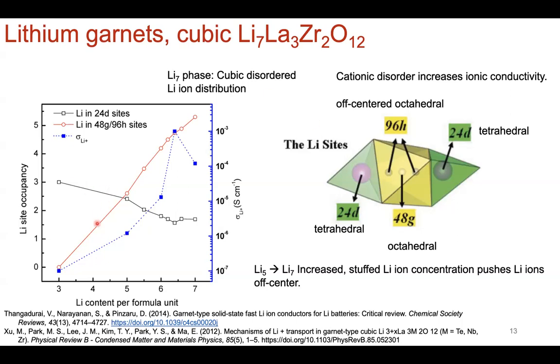Okay, so the relationship that's shown here in terms of the lithium site occupancy, as well as the lithium ionic conductivity, here shown in blue, ion conductivity increases quite a bit as you increase the lithium content per formula unit. So going from 3 all the way up to 7, although there are no error bars here. So I would take the general trend is that lithium ion conductivity increases with lithium concentration in these garnet type structures. So one of the reasons why you see people synthesize the Li7 lanthanum 3 zirconate is for that reason, as opposed to a lower concentration of lithium in these types of garnet systems.